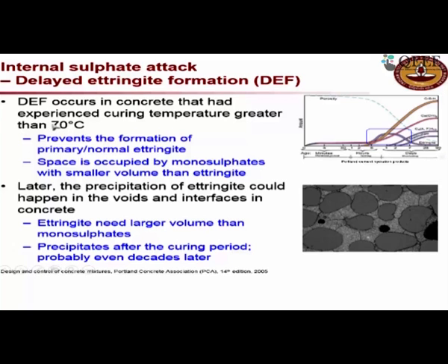If it is reaching more than 70 degrees Celsius during the curing period, then the ettringite which is formed will not form fully like in normal concrete. It will also have some monosulfates which are formed, but which occupy a smaller space. And then the problem is later, maybe after several years or even decades, when sufficient moisture is